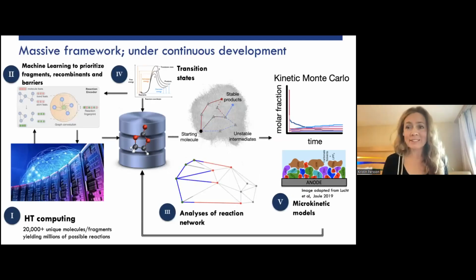We started building this infrastructure. It relies on high throughput computing, so we can calculate in the order of 20, 30,000 molecular fragments. They can be charged or non-charged, that's not a problem. We still can't calculate everything; even a couple of thousands of fragments will give orders of hundreds of millions of possible reactions, and then recombinant molecules tend to explode. So you still need machine learning to prioritize which bonds are likely to break or form, but that is a fairly robust machine learning problem.